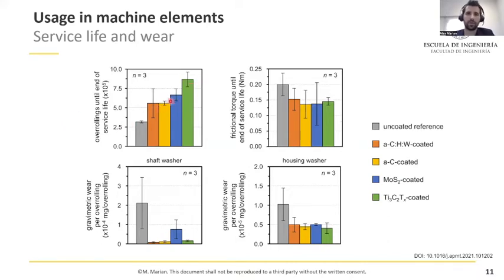So all the coatings substantially increased the service life, the two DLC coatings by roughly a factor of 1.8, MoS2 by roughly a factor of 2.1, and the MXenes by a factor of 2.7 compared to the reference. So that means that the service life of the MXene coated bearing was roughly 30% longer than that of the MoS2 and 55% longer than that of the DLC coatings. We can also observe that the gravimetric wear of the washers was reduced by up to 94% compared to the references, which was in a similar range to the DLC and even better than the MoS2.